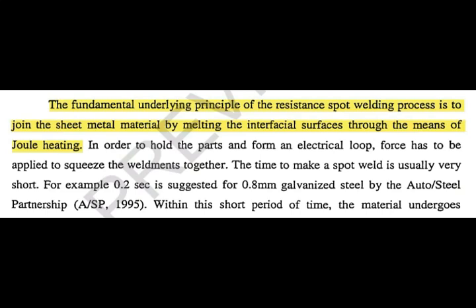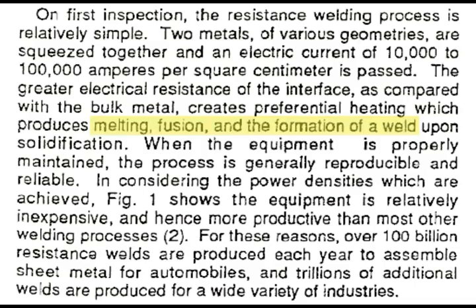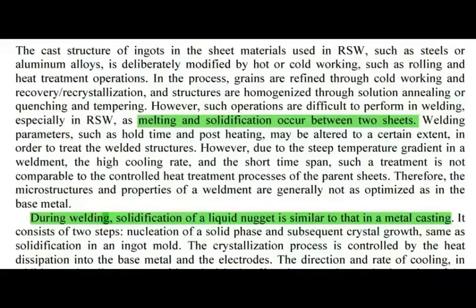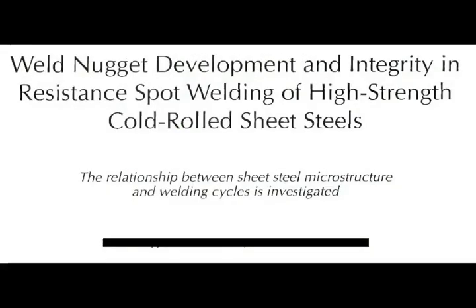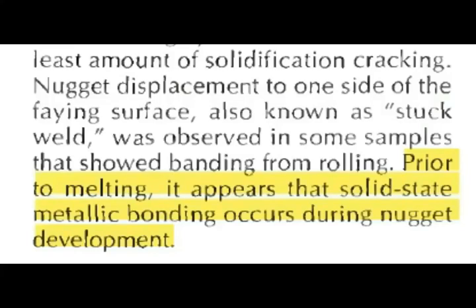The fundamental underlying principle of the resistance spot welding process is to join the sheet metal material by melting the interfacial surfaces through the means of Joule heating. Melting, fusion and the formation of a weld. Melting and solidification occur between two sheets. During welding, solidification of a liquid nugget is similar to that in a metal casting. Prior to melting, it appears that solid-state metallic bonding occurs during nugget development. They almost figure out that you don't have to melt in order to weld.